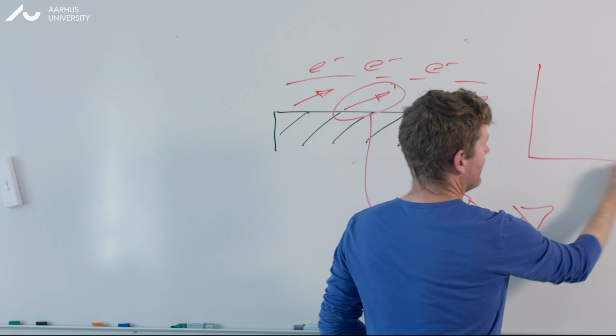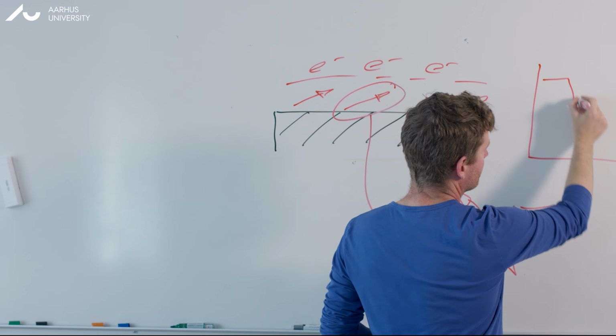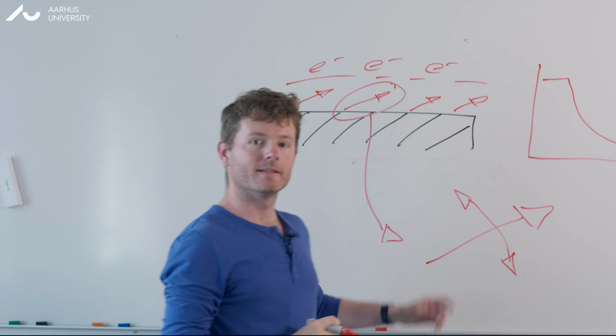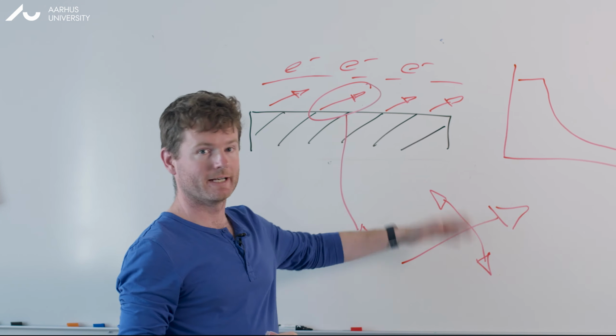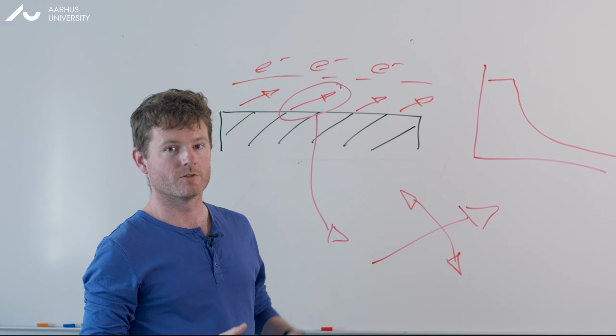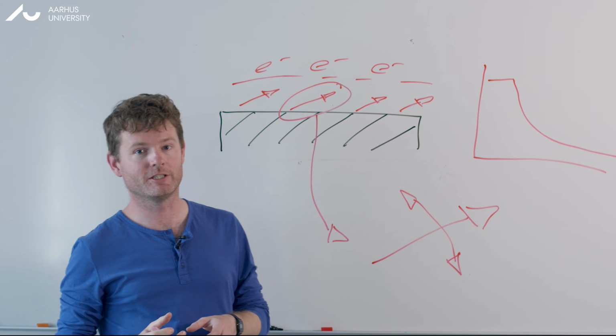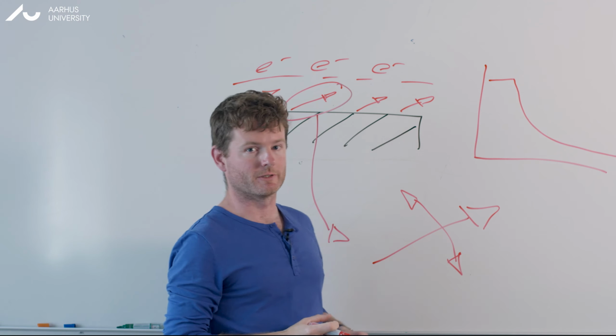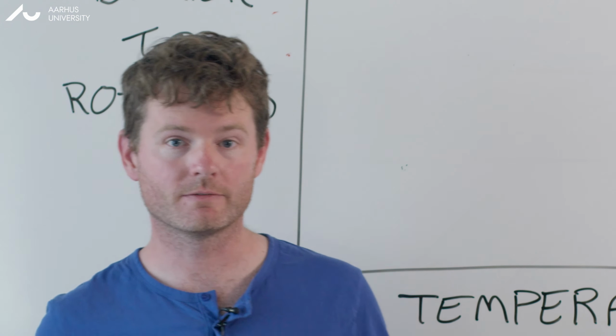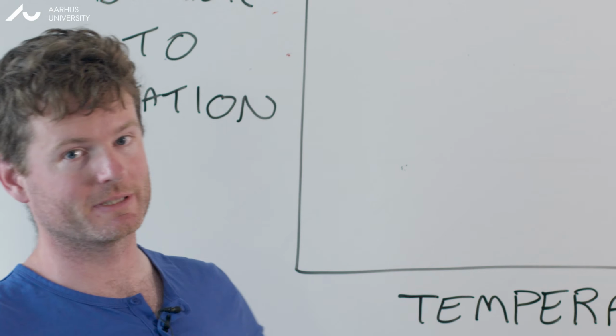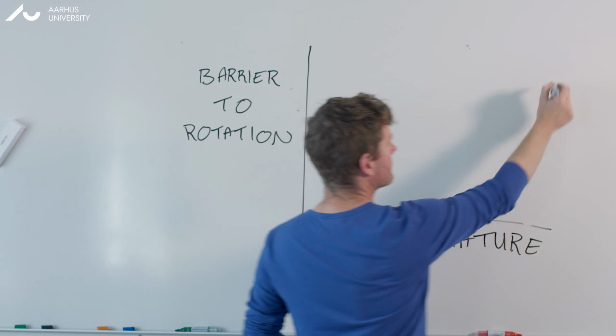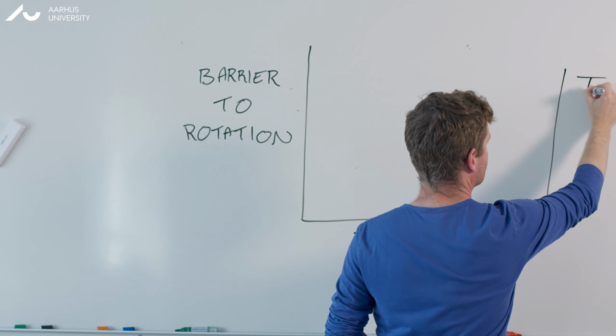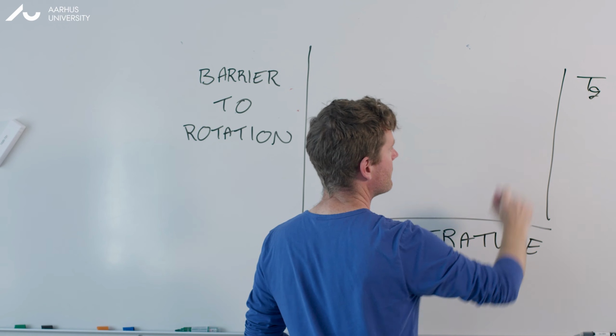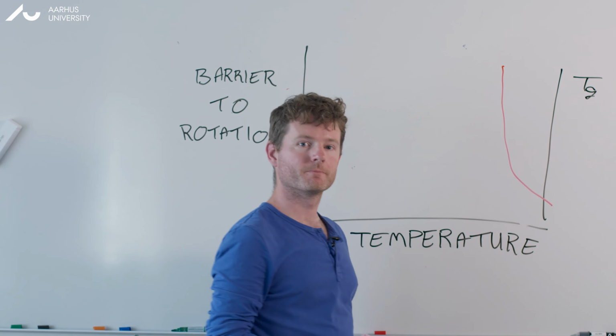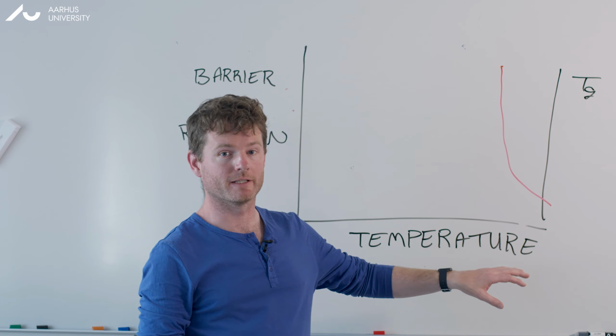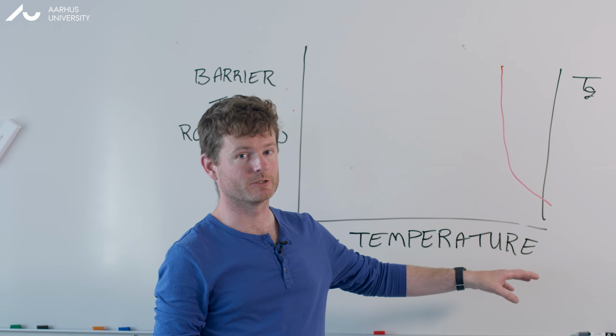We can measure the rate of this polarization decay as a function of time, and it directly tells us the rate of molecular rotation. So we use this to calculate the activation barrier towards molecular rotation in supercooled films. What we observed was that molecules rotate in 2 separate temperature regimes. Close to the glass transition temperature, molecules rotate much faster. This is accompanied by diffusion, as measured by the neutron scattering measurements.